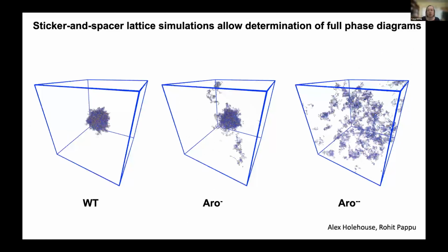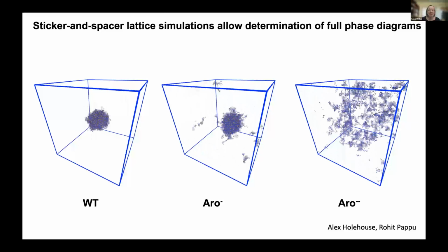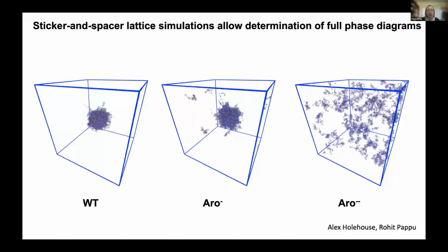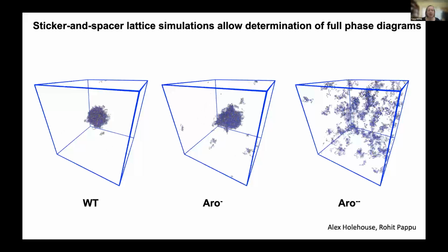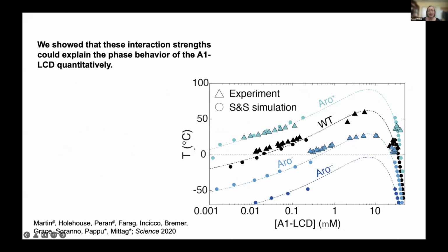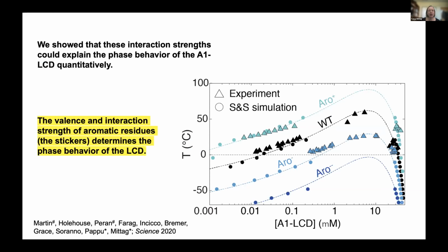That then allowed them to do stickers and spacers lattice simulations, where they put a number of chains into a box and simulated their behavior with the interaction strength that they had extracted from our experimental data. And that allows the determination of full phase diagrams. And these fit our experimental data here as triangles, in fact, very well. So that means that the aromatic residues are really important for this phase behavior, right? Because we were able to recapitulate the phase behavior with these parameters. What it, of course, also showed was indeed that the valence and the interaction strength of the stickers, in this case the aromatic residues, determines the phase behavior of these low complexity domains as we expected.